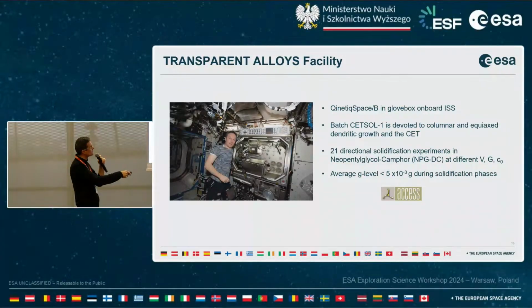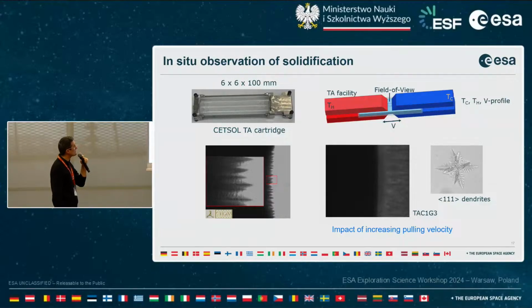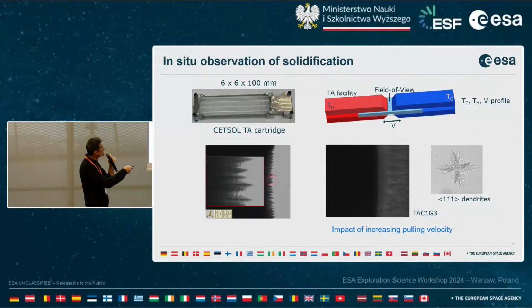since, again, with a directional solidification configuration, we can control each of them independently. And the gravity level was very good for these experiments. So here are some examples of some pictures of the cartridge. So you can see here the cartridge where the alloy is installed. Here is the schematic again of the directional solidification furnace, with in the same way a cold zone and a hot zone, and the sample in between, and the field of view will be over here in between the hot and the cold zones.